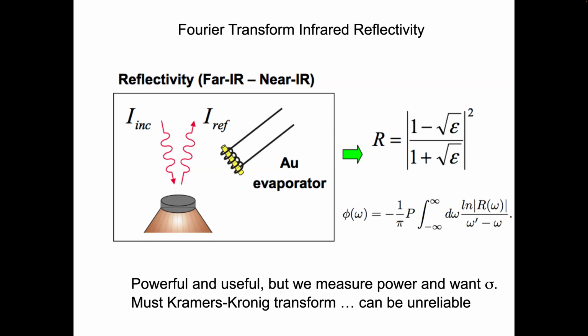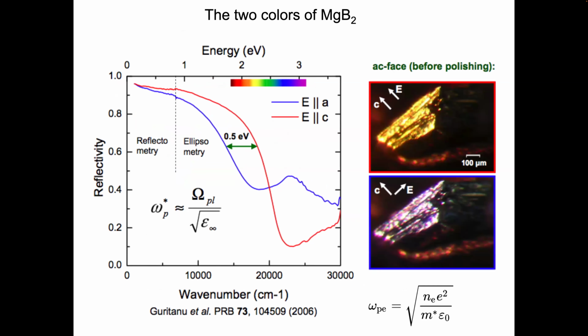It's a good technique, but it's a little, if you will, dumb, because even if I care about some superconductor which has milli-eV scale excitations, I have to measure out to electron volts in order to have this integral work, because technically and formally the integral goes from minus infinity to infinity. But it still can be done, and so this is an experiment that was done some years ago on magnesium diboride in Dirk van der Marel's group.